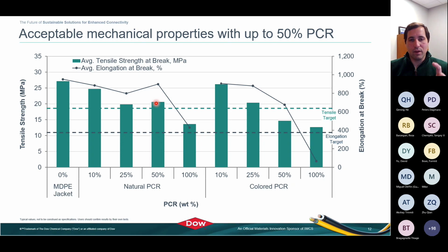So, definitely see up to 50% is fairly good. 25 to 50 could work, if optimized. But then in here where you look at the colored, again, when we consider worst case based on how different the sources could be, you see the drop off pretty dramatically, particularly in the 100% itself. But with good performance up to about the 25%, which is, in many cases where you might see PCR even in other applications, that loading is considered acceptable and useful from a sustainability point of view.